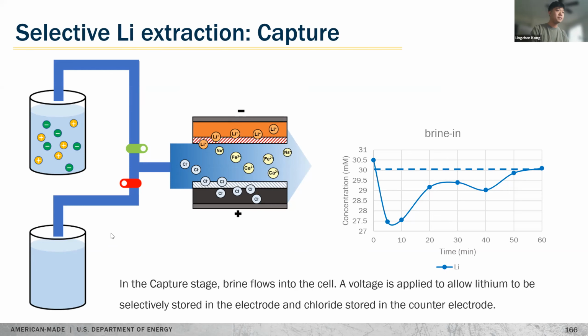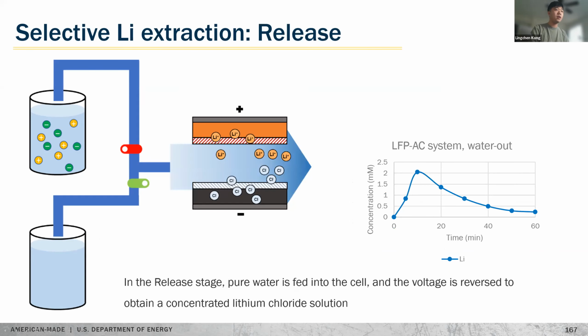Next slide, please. After we get the lithium extracted into the electrode, in the release process we switch the feed from the brine to pure water and reverse the voltage, and the lithium is released back to the water, giving concentrated lithium chloride. Then we feed the lithium chloride into another electrochemical process and obtain lithium hydroxide just by electricity input. Next slide, please.